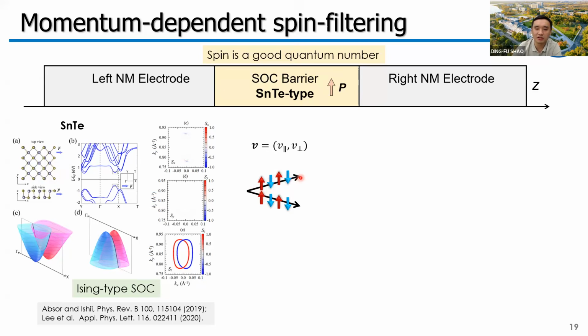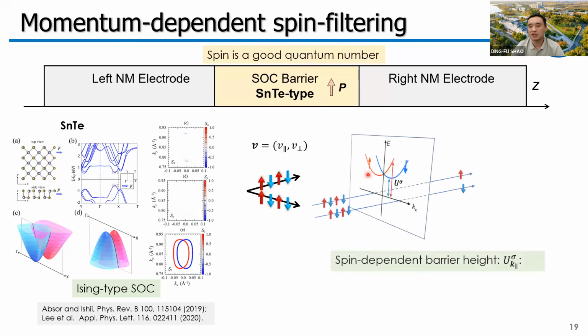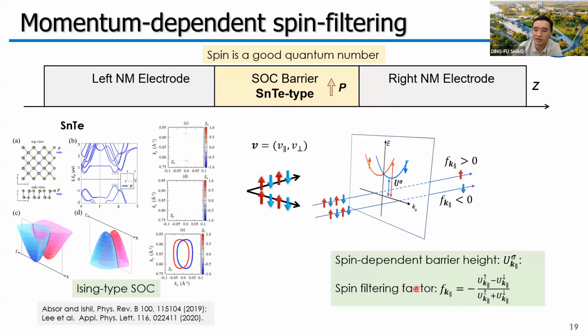In each velocity direction, the numbers of spin up and spin down electrons are equal in the left electrode. During the tunneling, because in the barrier we have very strong Ising type spin-orbit coupling, the tunneling barrier height for spin up and spin down electrons is different. We can then use the tunneling barrier height to define a spin filtering factor F. For a positive F, the spin up electrons tunnel and the spin down electrons are majorly filtered out. For a negative F, the transmission is majorly contributed by the spin down electrons.